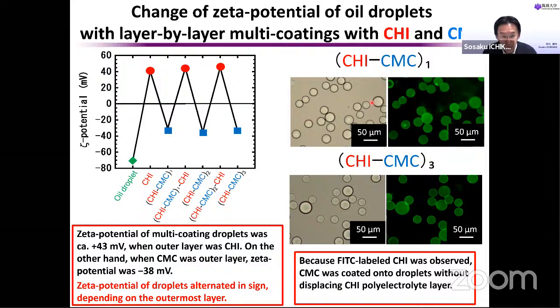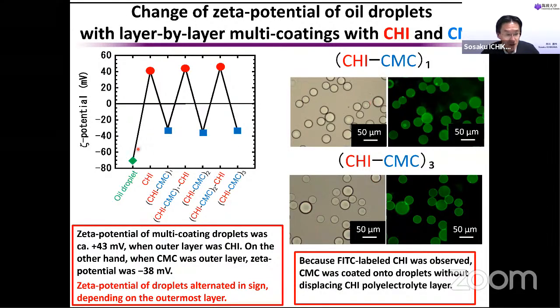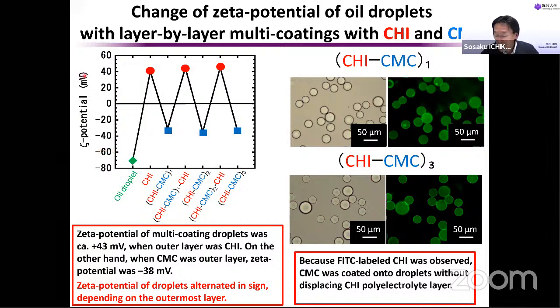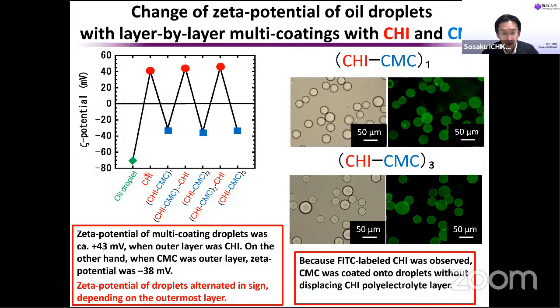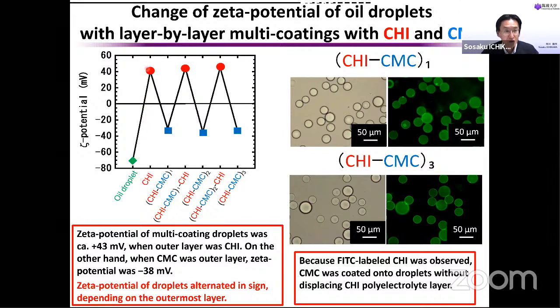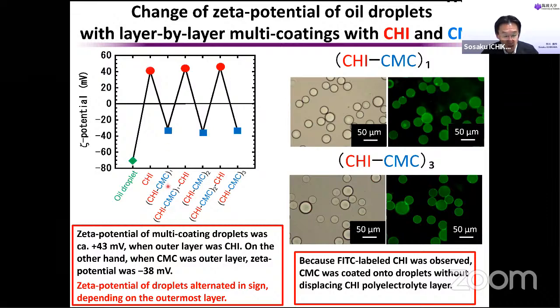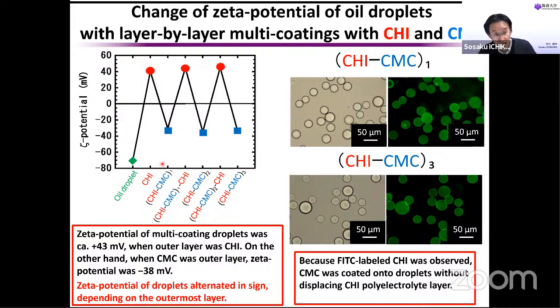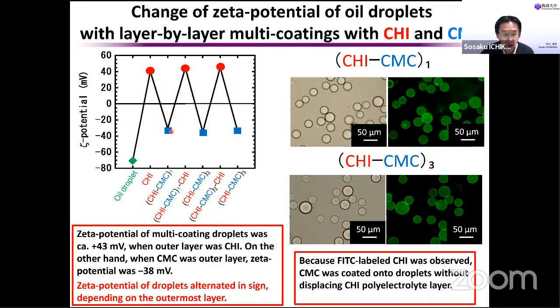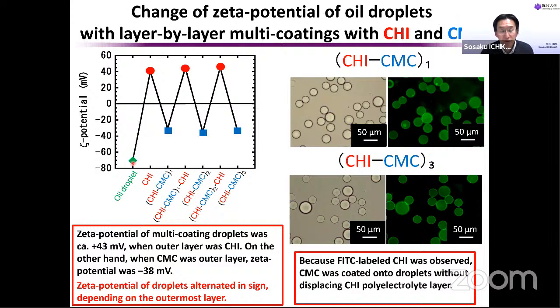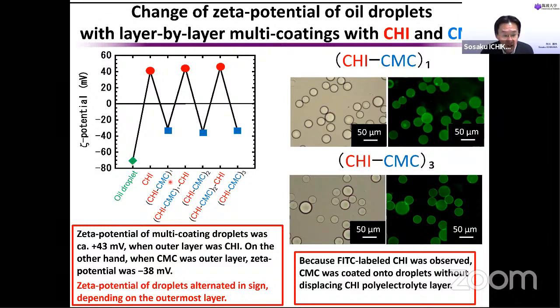This is a typical example of this layer by layer coating. This is the change of zeta potential. It means the surface charge of the oil droplet by layer coating. First, the oil droplet is highly negatively charged, but after the coating of chitosan, the surface charge changed to positive because the chitosan has a positive charge. After the coating by carboxymethyl cellulose, it changed to negative because CMC has a negative charge. So as you can see, the surface charge depends on the final coating material.